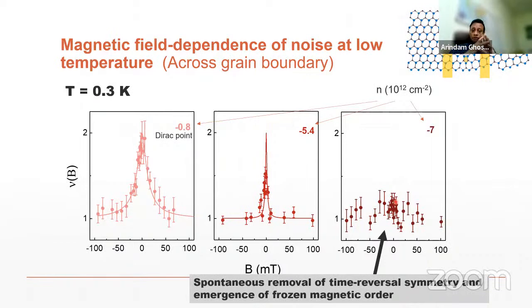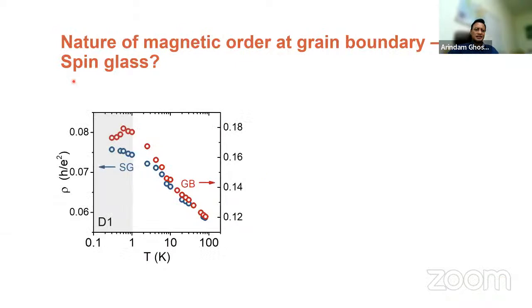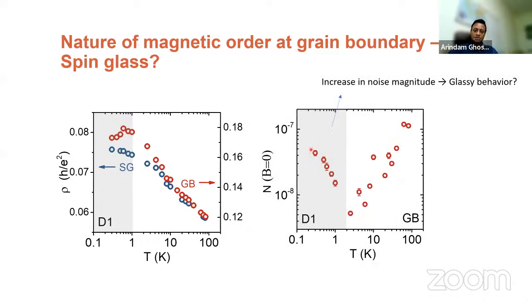So we have looked at it, and we believe that this is possibly a magnetic order at the grain boundary, probably forms a spin glass phase, and because the noise increases rapidly at lower temperature, below 1 Kelvin or 2 Kelvin, and possibly leads to a glassy behavior in graphene when disordered. So that's quite interesting. It's still in process.